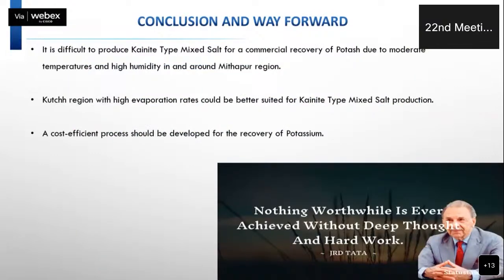So in conclusion, it is difficult to produce kainite type mixed salt for a commercial recovery of potash due to moderate temperature and high humidity in and around Mithapur region. Kutch region with high evaporation rates could be a better suited area for kainite type mixed salt crystallization. A cost efficient process should be developed for the recovery of potash. So we need to work on this further to make it a commercially feasible venture. Thank you.